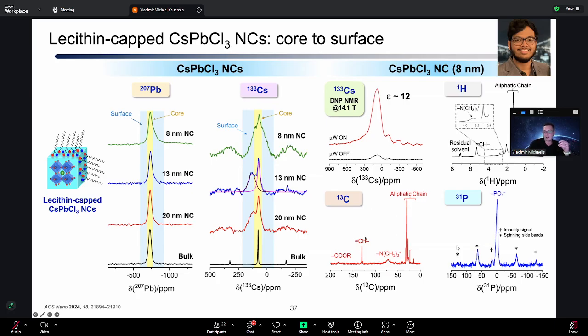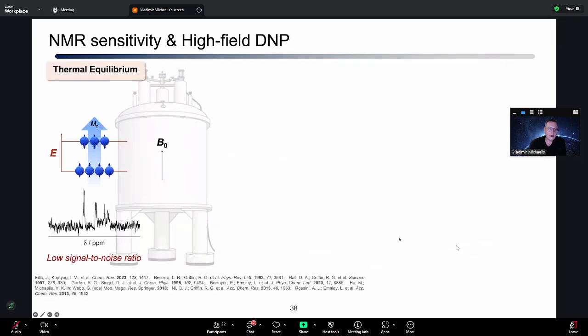Likewise, here you can see the aliphatic chain of the carbon is really nicely resolved. This is demonstrating that that chain is moving, or is mobile, on the surface. There's nothing holding it back. But the phosphate group has some broadening and what's called CSA. What this indicates is that that site is binding covalently somewhere, or it's suggesting it's binding covalently somewhere. So this is important. The organic component is dynamic, but it definitely looks like the anion is coordinating to something. Okay. Now, because it's only the thin surface layer, one of the problems with NMR at times is its overall sensitivity.